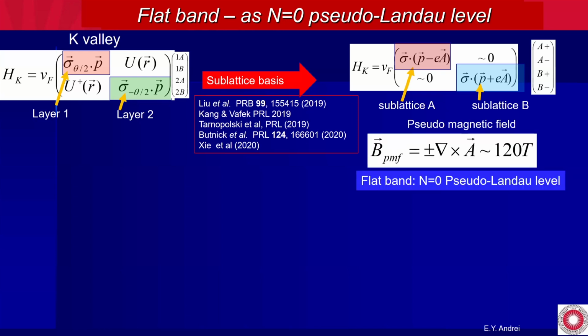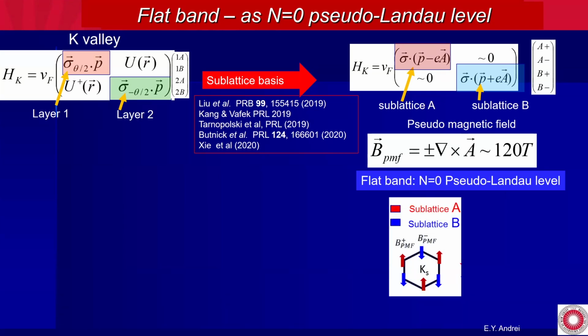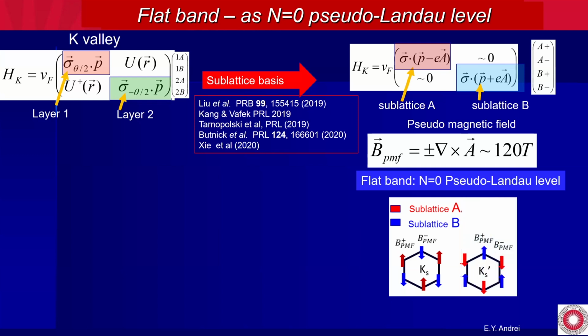It is, of course, very inhomogeneous, but the maximum value is about 120 Tesla, one can estimate, and they have opposite signs in the two sublattices. That means that you will have Landau levels, or pseudo Landau levels, without applying a magnetic field. Okay, and this pseudomagnetic field points in opposite direction in the two sublattices. So this was for the K valley. You see here, sublattice A, the pseudomagnetic field points up, or we can say the Chern number is +1, and sublattice B, it points down. Of course, we cannot forget the K prime valley, and there everything is time reversal symmetric. So in the K prime valley, sublattice A has a pseudomagnetic field that points down, and sublattice B has a pseudomagnetic field that points up, okay?